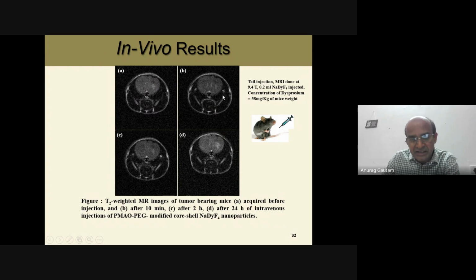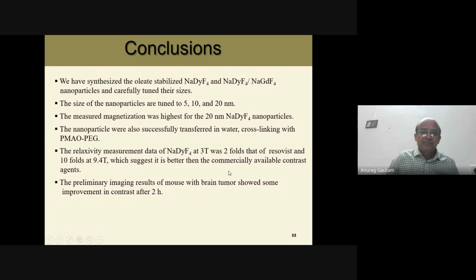This is just imaging after 10 minutes, and then it is still darkened compared to this one after 2 hours, but after 24 hours we believe the particle moved out from there, so it becomes more whitened, back to normal position. So the conclusion we have: we synthesized oleate nanoparticles, and the size was varied, and we measured the magnetization, highest for the bigger nanoparticle. Then the surface was coated, and then we imaged that particle and found decent contrast.